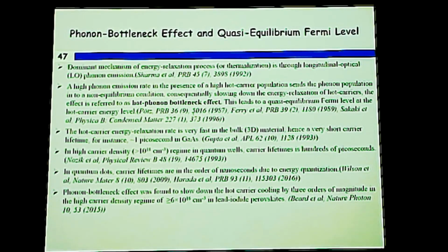And when that happens, for photoexcited carriers in bulk material, the carrier lifetime is very short, on the order of 1 picosecond. However, in quantum wells, where there is one-dimensional energy quantization, and when there is high carrier density, the carrier lifetime becomes longer, hundreds of picoseconds. And in quantum dots, the energy confinement is in all three dimensions. So there is a high energy mismatch between the phonon energies and the quantum dot energies. So the carrier lifetime is much longer, in nanoseconds. And not just in semiconductors, there is also a different material, a kind of salt, lead halide perovskites. People are studying this material for solar cell applications, and they want to see how to increase the lifetime of the carrier in solar cells so that the collection efficiency becomes higher.